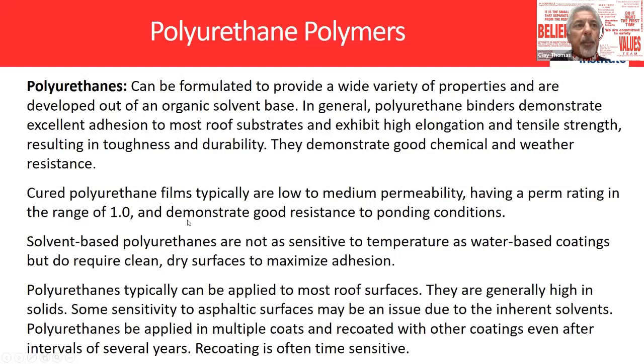Less permeability in a polyurethane, around 1. The acrylics can get high. The acrylics will absorb a lot of moisture too. I mentioned when I did my test, I left my 2 samples, my acrylic out and I left my silicone out. Well, when it rained and they got wet, my acrylic grew because it absorbed moisture. My silicone did not. It stayed intact.